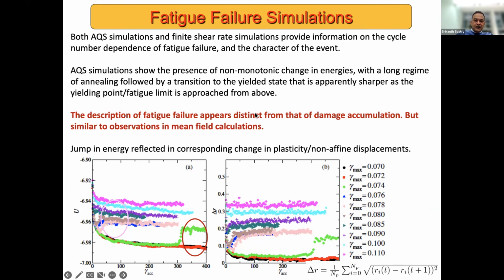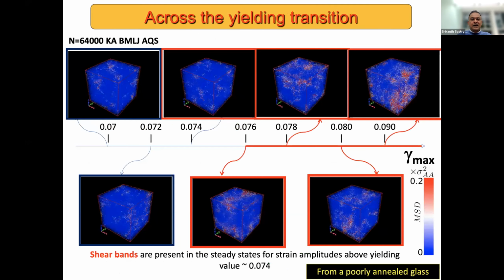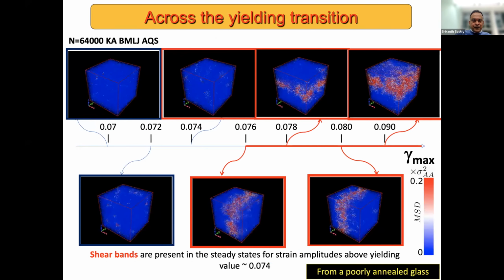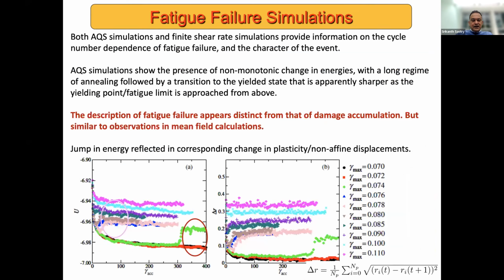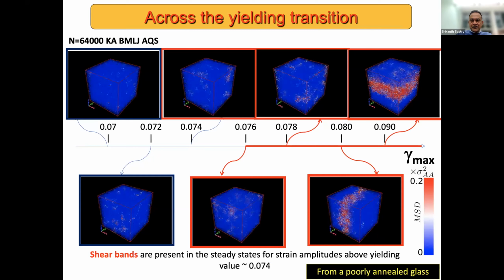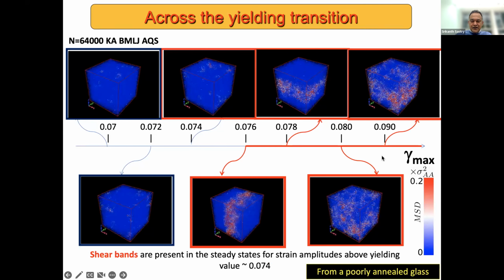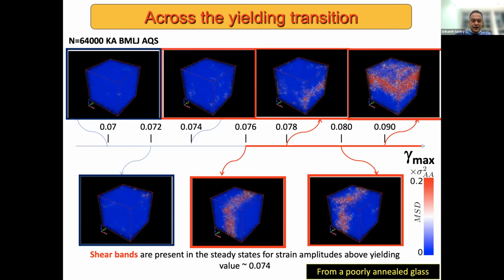And this description of fatigue failure appears to be very different from what people seem to say in the literature. And I say this with a little bit of hesitation because I'm not completely clear what picture people have in the materials community, but there is a description of failure in terms of damage accumulation, which seems to suggest that it's a gradual process. So from one cycle to the other, you accumulate damage, and this leads to failure eventually. Okay, this doesn't look like what you see in amorphous solids. I'll skip this, except to say that when you have these sudden jumps in energy to the yielded state, these are accompanied by the formation of what are called shear bands. Okay, this you see on the right side pictures or videos in this panel.